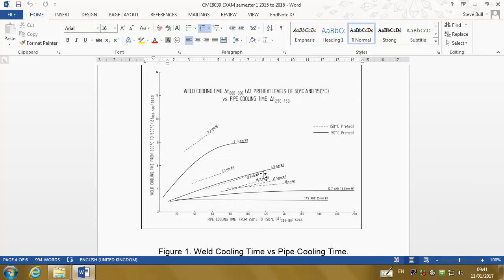Where you've got something like this here, the cooling rate is going to depend upon the local conditions that are around the outside. So in this case, it's much more difficult to control the cooling rates than in this case, because there's a very fixed relationship. So the implications are that it's easier to actually control the cooling rate in thick pipes or very thin pipes, but the ones in the middle, because you might have this transition behaviour, that's not necessarily so easy to control.